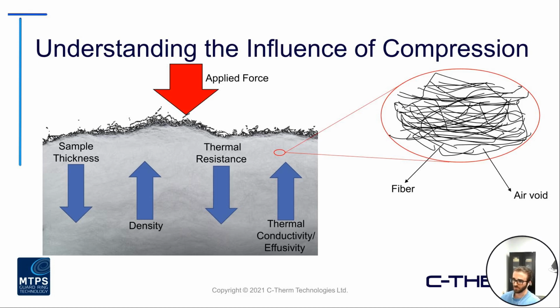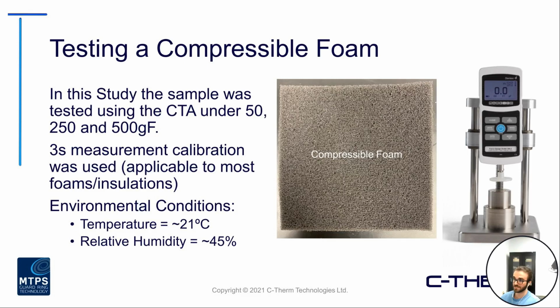And we'll take a look coming up at a quick data set that was collected on a compressible foam. In this study, we tested the sample under varying force loads from 50 to 500 gram force. The calibrations used had a 3-second measurement duration. This is really good for most of those foams and insulators that may be a little more dense in nature. And the environmental conditions, again, always good to take note of those. Temperature is approximately 21 degrees Celsius and approximately 45% relative humidity for this test.